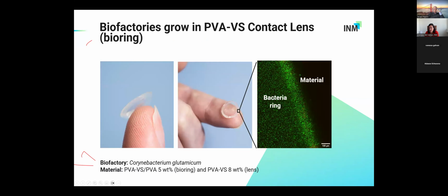So this is a lens which contains the biofactories. It looks like a normal lens. Outside in the ring, you would have the biofactories, and you zoom in. What you see is that the bacteria are contained, so the biofactories are contained in the ring. And they can actually not grow outside. I will show you later on. And here you see the composition. So it's engineered Corynebacterium glutamicum, and PVA 5 and 8%. 5% is in the bio-ring and 8% is the lens.